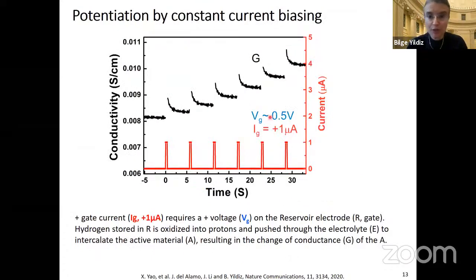And let's see if it works. So this is a few pulses that I'm showing to you now, gate pulses of +1 microamp. And after each pulse, we are monitoring the conductivity of the tungsten oxide layer. And after each pulse, we are also opening the circuit. It's a non-volatile process because once you open the circuit, you block the path for electrons to escape. So after each pulse, we see progressive increase in the conductivity of the channel material. So upon each pulse that brings protons into tungsten oxide, we protonate the tungsten oxide and increase its electronic conductivity. So that's a few pulses.